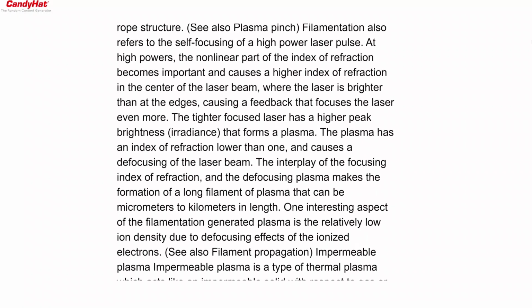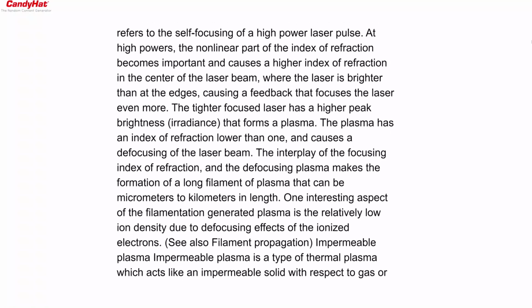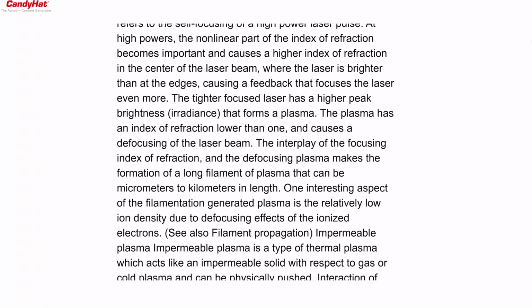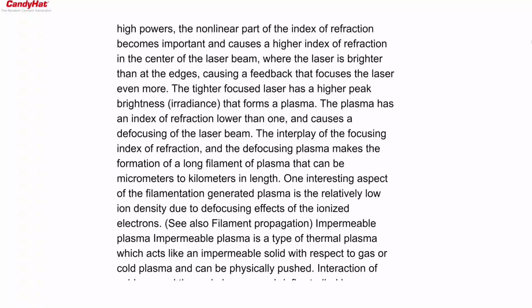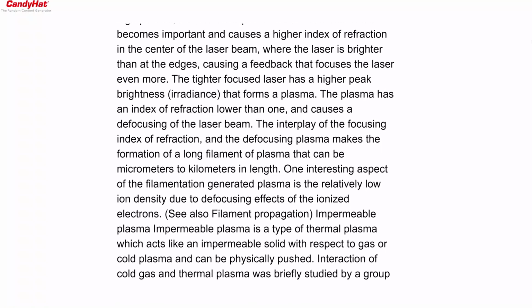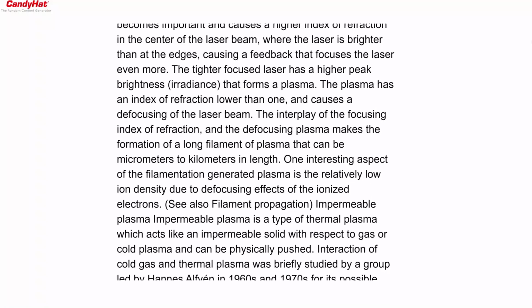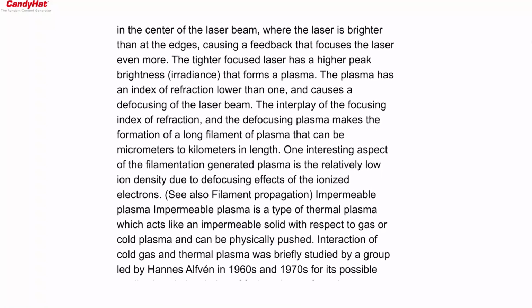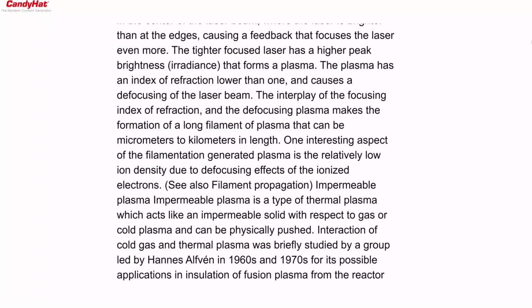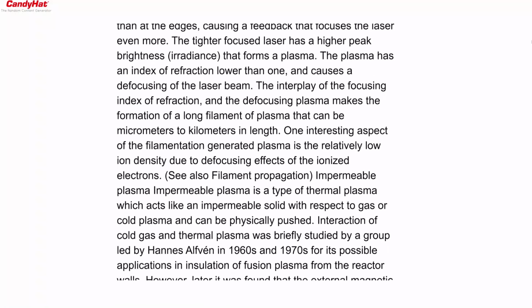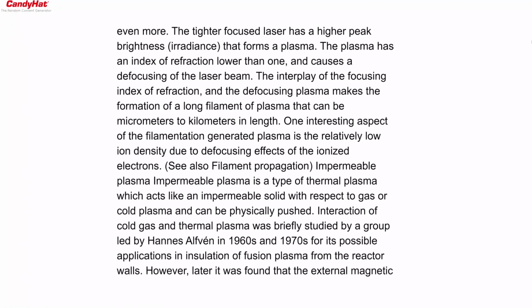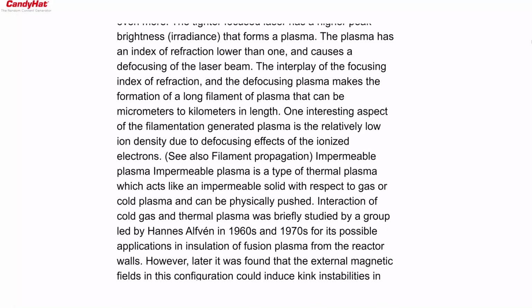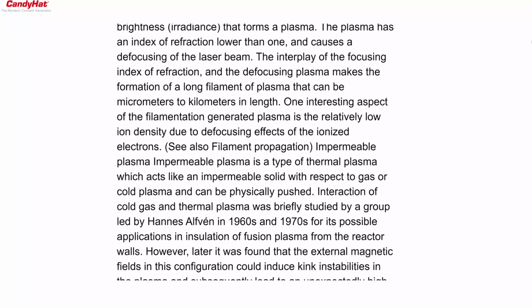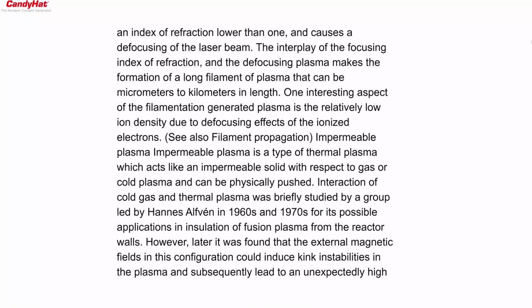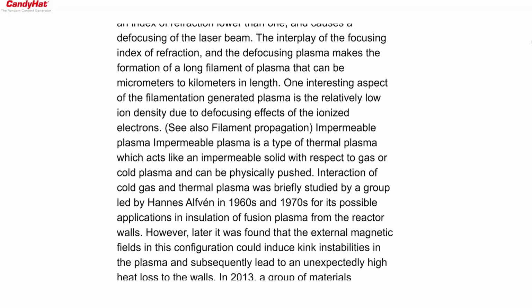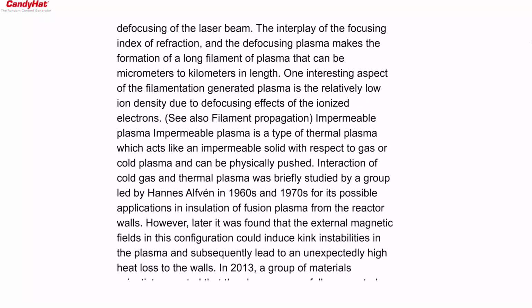The tighter focused laser has a higher peak brightness, irradiance, that forms a plasma. The plasma has an index of refraction lower than 1, and causes a defocusing of the laser beam. The interplay of the focusing index of refraction and the defocusing plasma makes the formation of a long filament of plasma that can be micrometers to kilometers in length. One interesting aspect of the filamentation-generated plasma is the relatively low ion density due to defocusing effects of the ionized electrons. See also filament propagation.